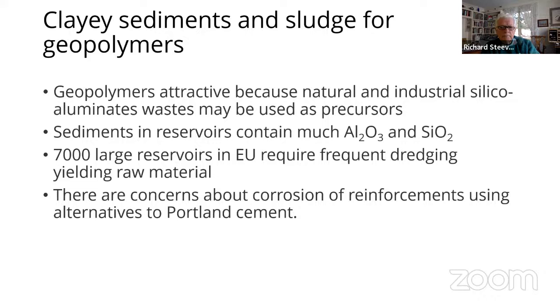And so again, this issue with these voids being created in the cement is a concern because voids allow water to infiltrate concrete, and then that attacks the structural steel that is oftentimes included in the concrete itself.